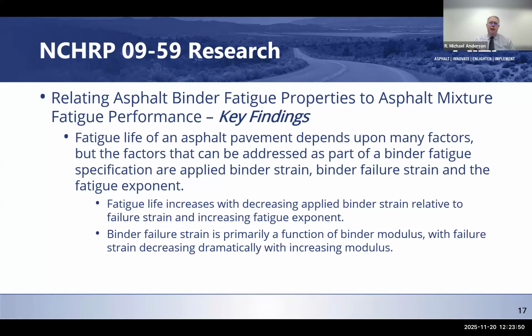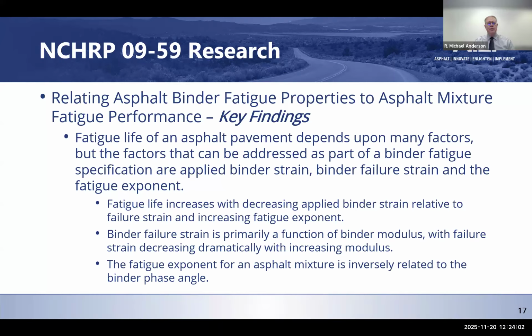The binder strain itself is primarily a function of binder modulus, so G star. Failure strain decreases dramatically with increasing modulus. And fatigue exponent for a mixture is inversely related to the binder phase angle. In other words, you get a higher fatigue exponent with a lower phase angle.